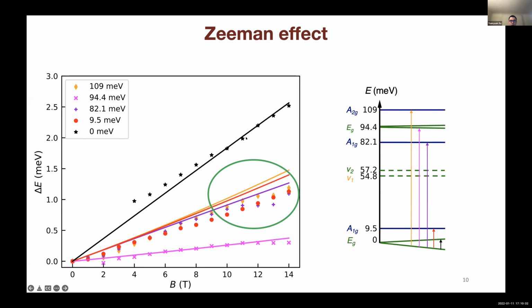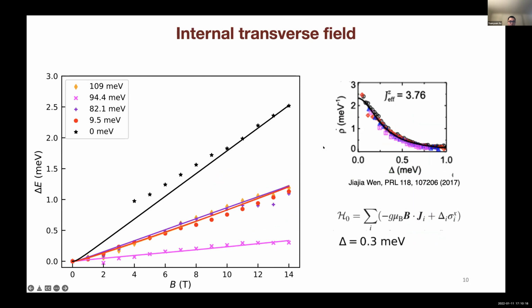The experimental data generally agrees with the calculation, but there is a little discrepancy for the transitions from the lower state to the high energy singlets. So in order to overlap these three lines, we borrowed the idea from previous neutron scattering work, the existence of an internal transverse field due to some lattice effect, so we can improve the fit. The origin and the mechanism of the internal field is still under exploration.